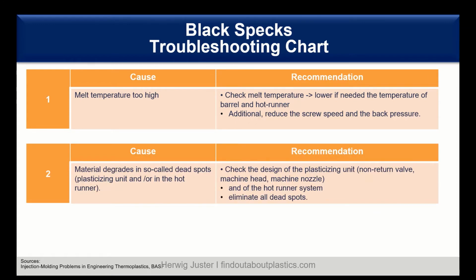Then another cause is the material degradation due to so-called dead spots. So you can have several dead spots in the plasticizing unit itself and or in the gating and in the hot runner system. Here, first thing we can do is also check the design of the plasticizing unit. So what non-return valve are we using, or what valve system in general, how is the machine head designed, how is the machine nozzle, are there some critical areas. Then we can check the hot runner system and identify the dead spots and try to eliminate them by changing the valves or different machine heads, or the whole machine itself if you have another machine available. The same for the gating system.